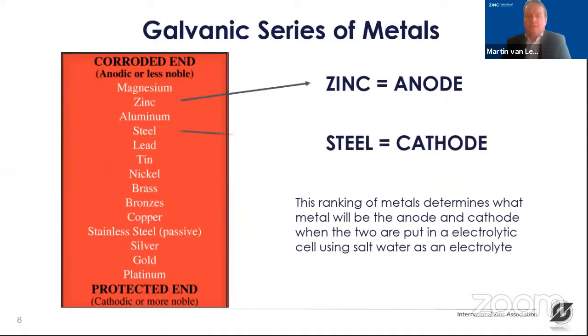But also, zinc is less noble than steel. If we look to the series of electropotentials of different metals, we can see that aluminum, zinc, and magnesium are less noble than steel. So they can protect steel in a sacrificial way if they are applied on top of the steel. Zinc, again, is less noble than aluminum, so it's better to apply a zinc coating than an aluminium coating on a steel surface. Aluminium coatings hardly provide any sacrificial protection to the steel because the voltage difference of electropotentials between aluminium and steel is not large enough to give steel the cathodic protection against corrosion. Zinc, in this case, will work as an anode and will sacrifice itself to protect the steel.